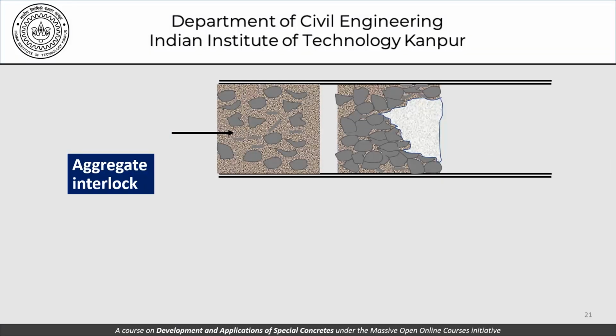This is another problem that happens, aggregate interlock. If we have this kind of concrete here and it moves the way it has been shown to be moving in the previous slides, we may have a situation like this. All this aggregate here forms an arch and blocks any kind of movement here. And that's one of the reasons why the diameter of these pipes should be somehow related to the maximum size of the coarse aggregates that you're using. That's one of the reasons. There are other reasons as well. And obviously we do not want this aggregate interlock, which is related not only to the maximum size but also the grading or particle size distribution as far as the coarse aggregates are concerned.